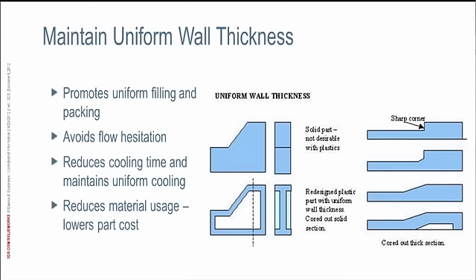That sharp corner will result in a stress concentrator, so stress will concentrate in that area and make the part likely to fail. Because of the abrupt transition, you might also experience flow hesitation where the thick section fills first and the thin section cools off. A little bit better: add a chamfer. Even better: a gradual transition from thin to thick. But really the best thing to do is core out the thick section — maintain a uniform wall thickness throughout the entire surface area of your part.